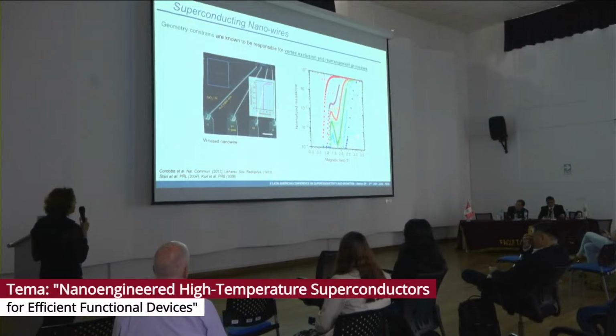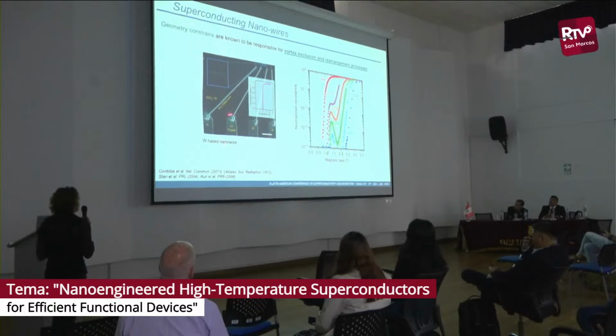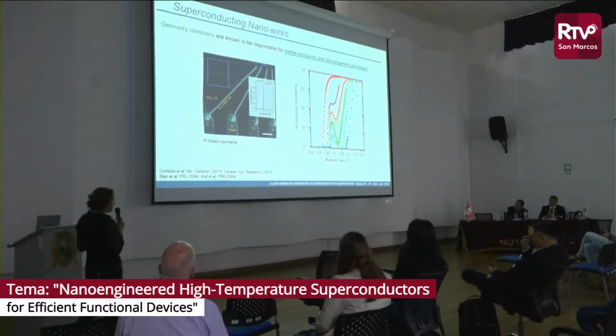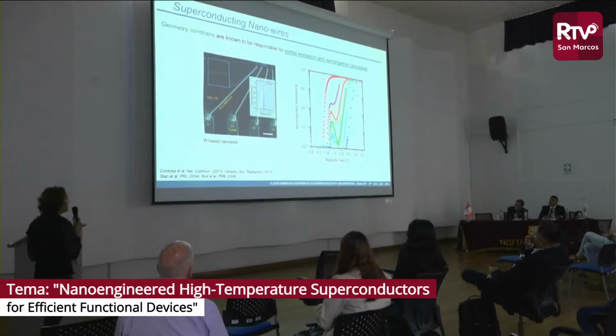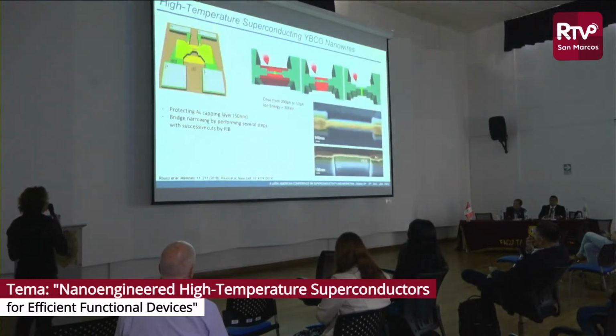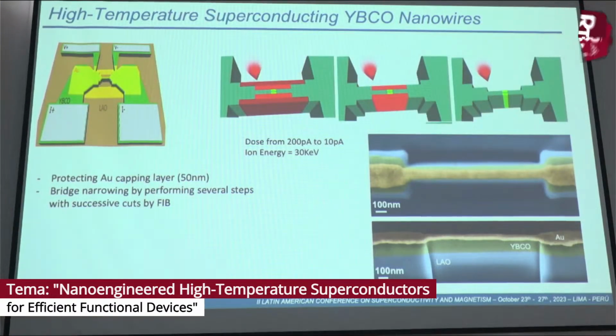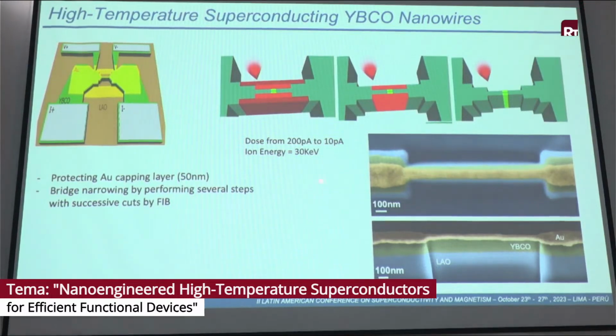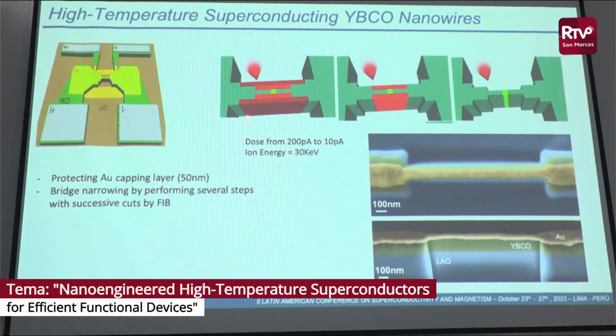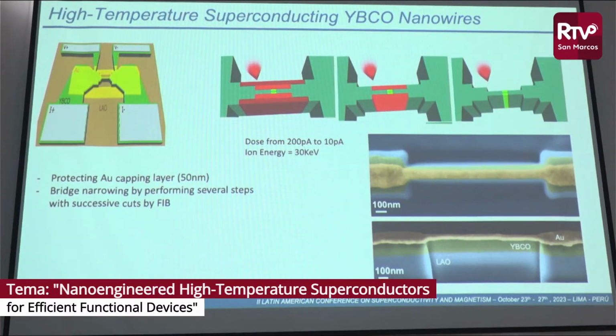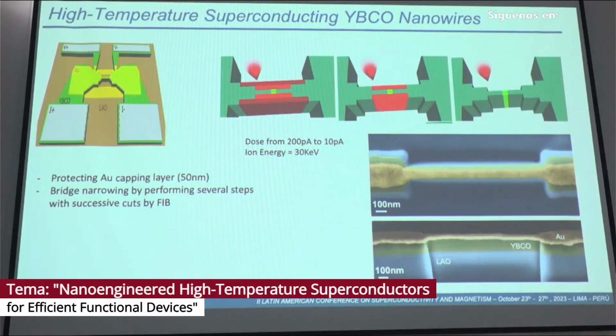the superconductivity, which were explored in nanowires, for example, in this work here, in nanowires based on low TC superconductor. We explored these kinds of systems in high TC, and what we perform is nanowires in YBCO. This is quite tricky because in YBCO we need to mill the system and to perform these nanowires by trying to not lose any oxygen or not having any implantation of gallium or something in the material that could damage the properties of the material.